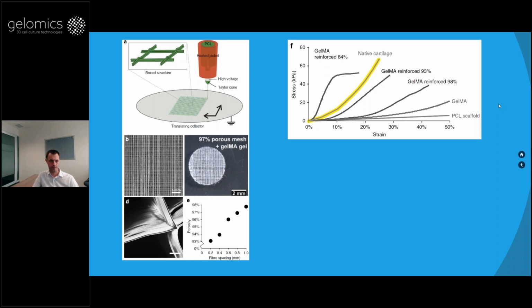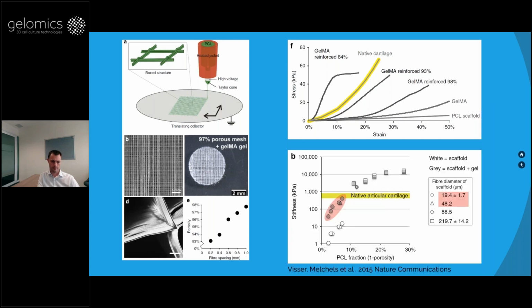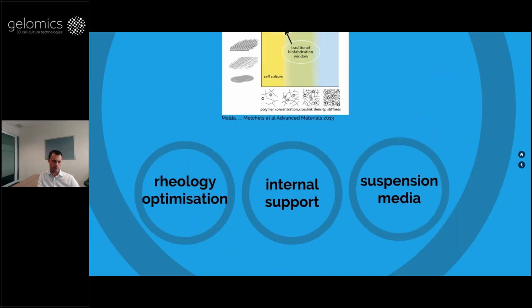a typical FDM printed PCL scaffold. So the 84% there is an FDM scaffold at the highest porosity we could attain, which is actually too stiff, and at 10% it fails. So that's not the best scaffold for cartilage. So these fibers really help to reinforce the gel and make something with similar mechanical behavior to cartilage.